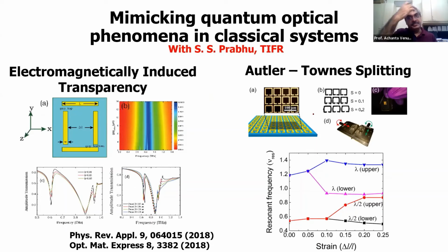This is in the terahertz system, so this is a classical system. It's a metamaterial. Here you have a metal rod in which we can excite a dipole. You can have a plus maximum here and a minus, negative, of the electromagnetic field here. The incident electric field polarization is along this direction, so you excite a dipole in this. This dipole is going to induce a quadrupole in these two rods.